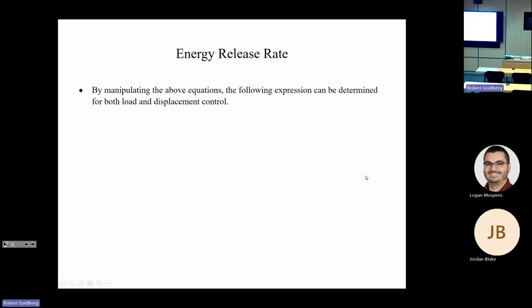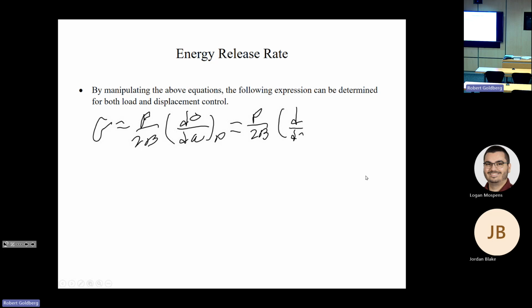we had. So for example, for the case of the applied load, we had the strain energy release rate is equal to the load over 2B times the derivative of delta with respect to A, all for the case of applied load. So we can substitute in from this expression here, we know that delta is equal to the compliance times the applied load. So we have P over 2B times the derivative with respect to A of the compliance times the load,